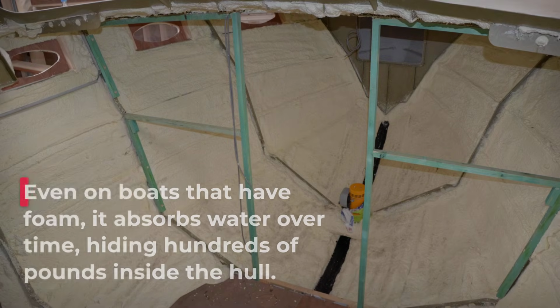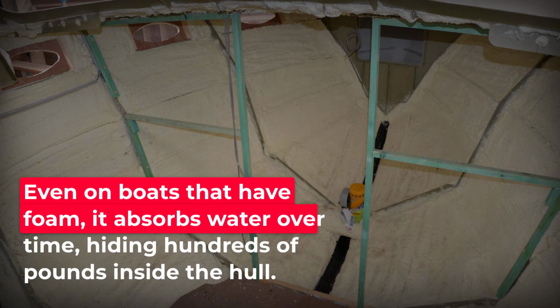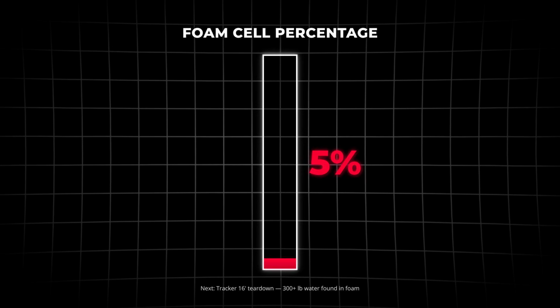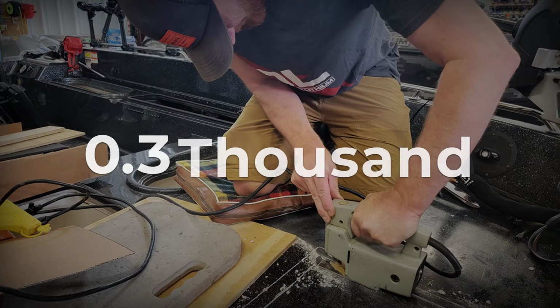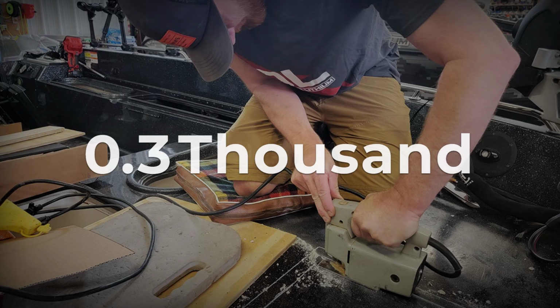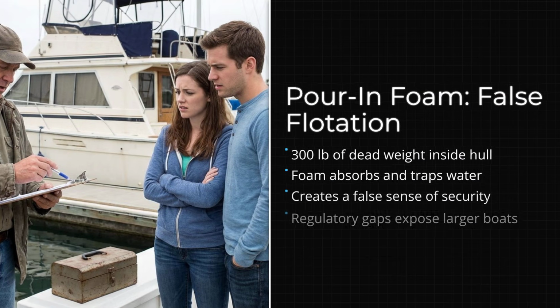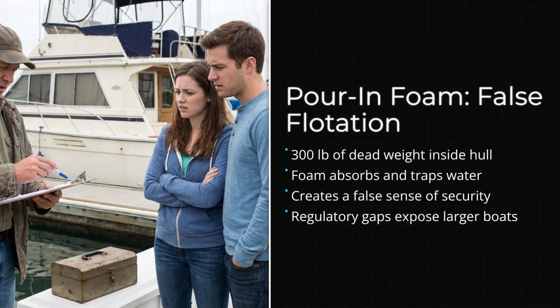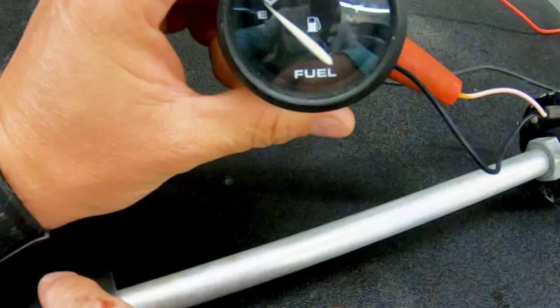Period. Even on boats that do have foam, the stuff absorbs water over time. 5 to 6% of the cells are open, creating pathways for moisture. A Tracker 16-footer that was torn apart yielded over 300 pounds of water trapped in its foam. That's 300 pounds of dead weight the owner had been hauling around for years without knowing it, burning extra fuel